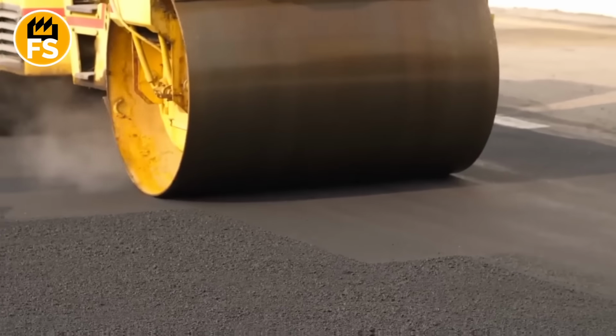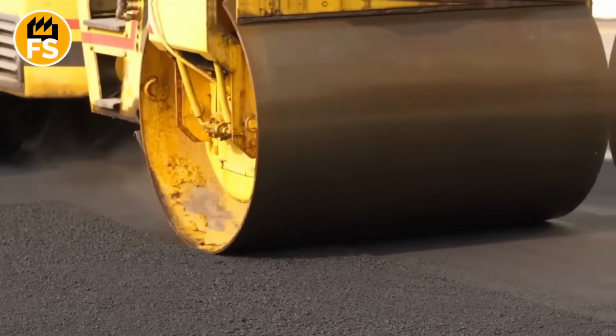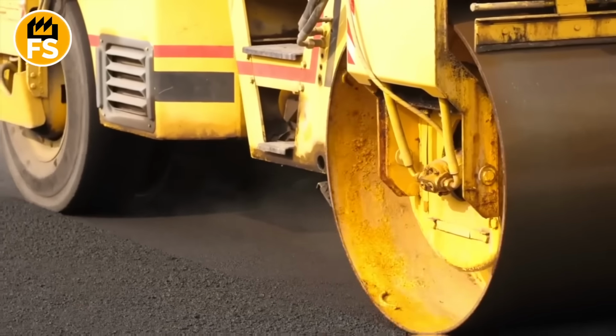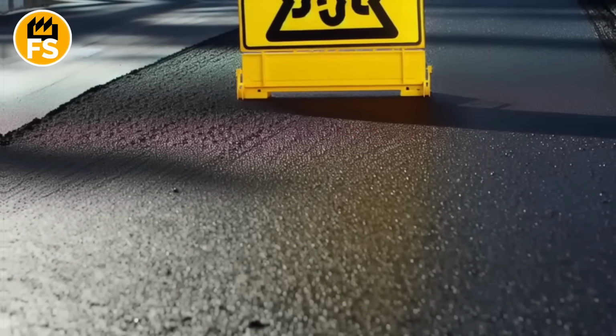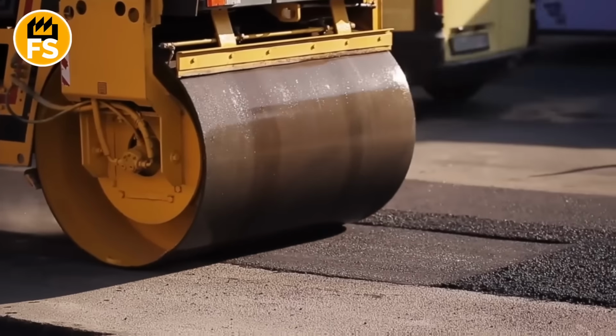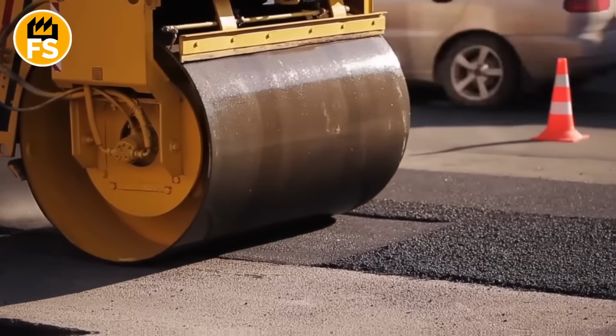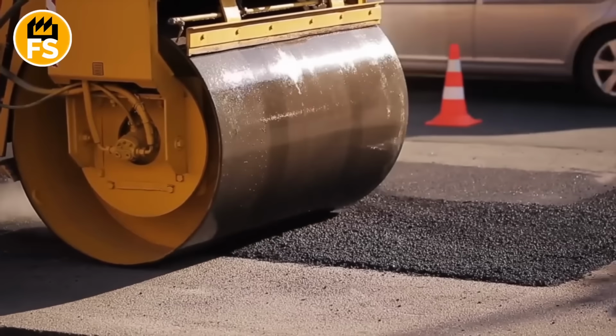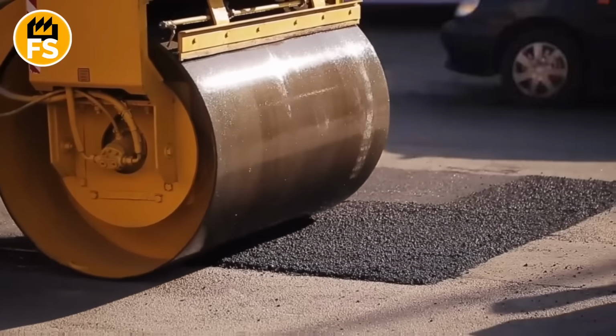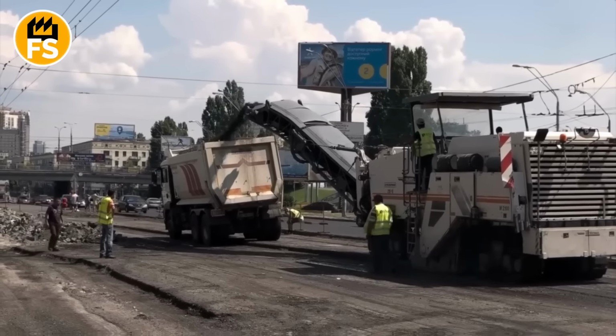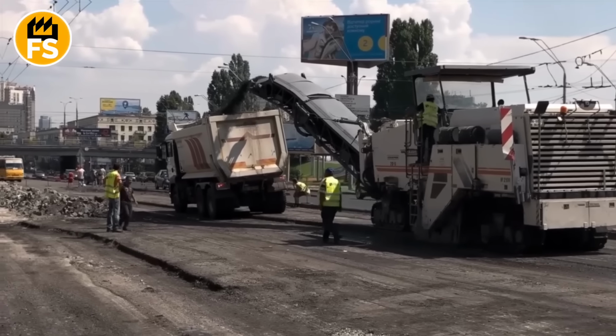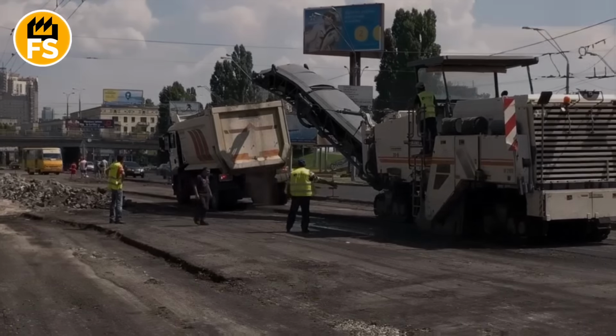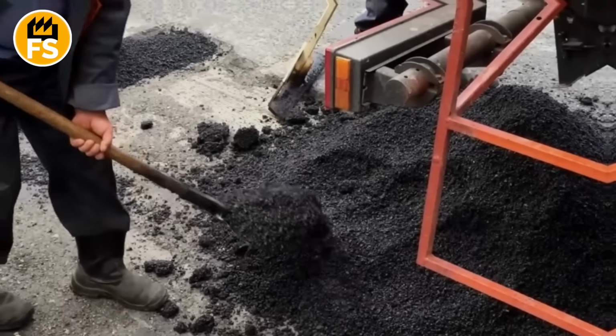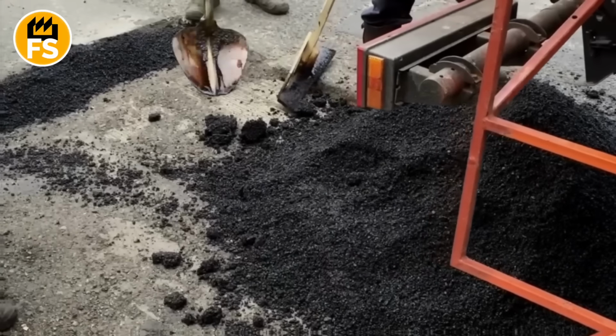roads decreased by approximately 40% during the first 2 years. Meanwhile, road surface service life increased on average from 7 to 10 years to 12 to 15 years before the first major repair. This significantly reduces overall infrastructure costs. Although initial polymer asphalt installation costs are higher by approximately 15 to 20%, long-term savings can reach 50% due to reduced repair needs.